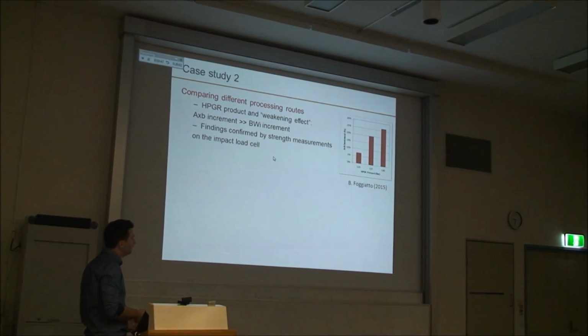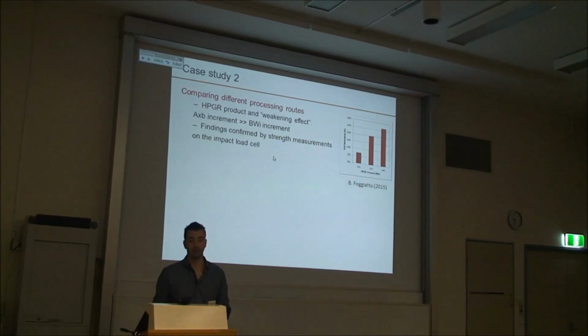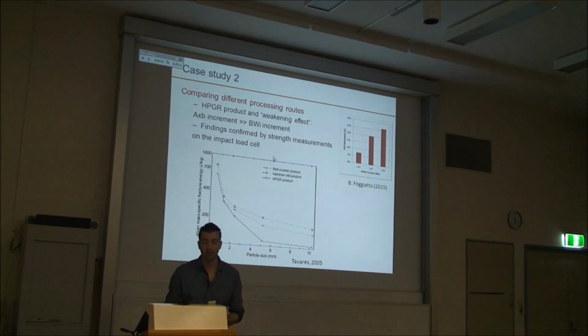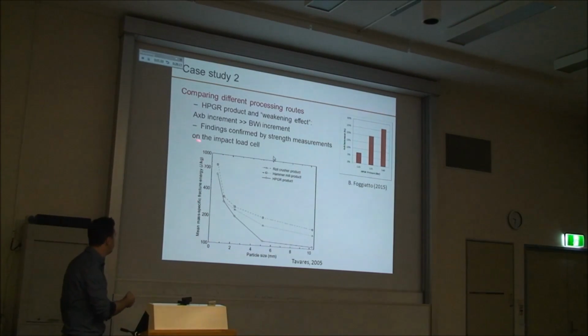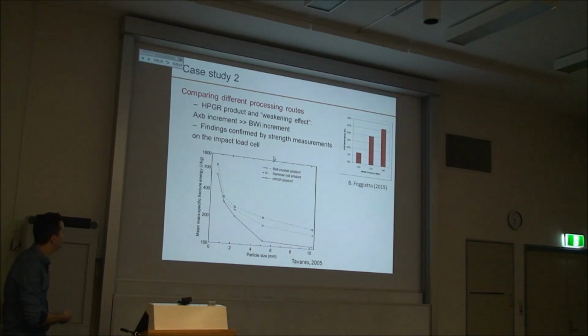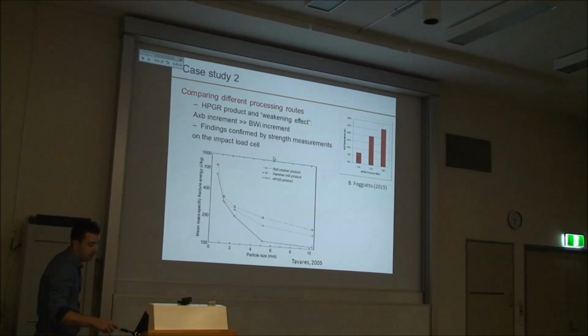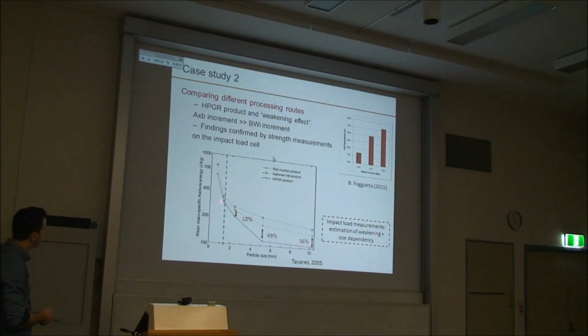So then I was wondering, okay, can strength measurement back that up? Can we confirm that by doing strength measurement? And I've used here Marcelo Tavares' data, which shows, again, the mass specific, the median specific fracture energy, so the E50, which is the property we're going to look at, versus size. This line here is the HPGR product, and those two lines here are crushed products, so not going through an HPGR. And what was found is that there is a critical size at about 1 to 2 millimeter. Well, the particle properties are roughly the same if they've been through a HPGR or through a crusher. But for larger particle size, that's where the HPGR product has a much smaller fracture energy, so a softer product, and the difference observed here was actually roughly in the same range as what Bianca observed.